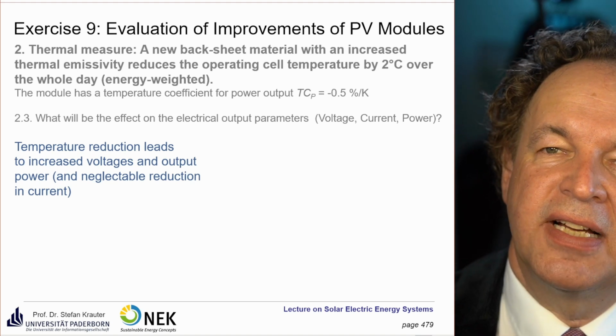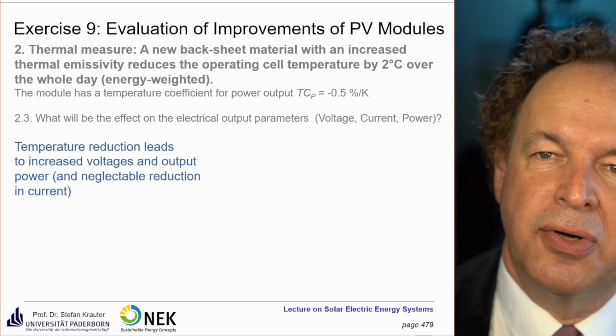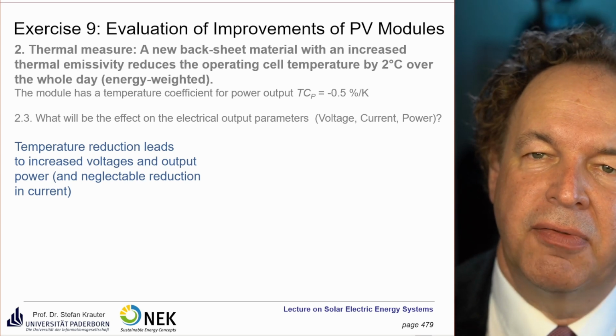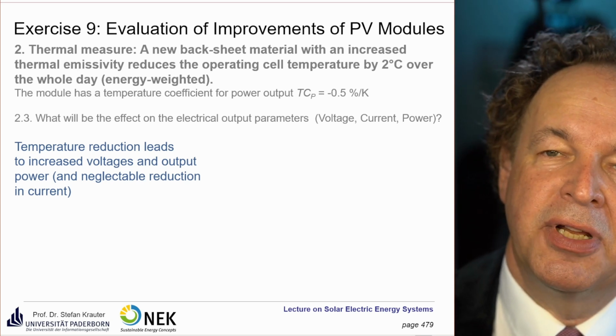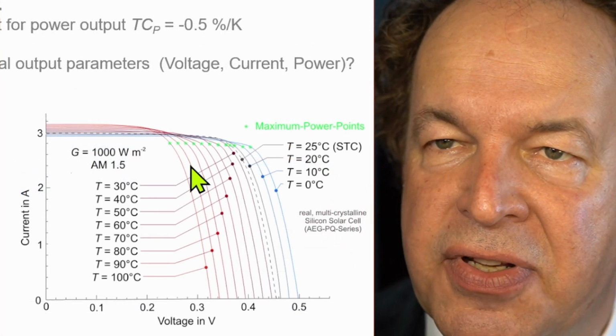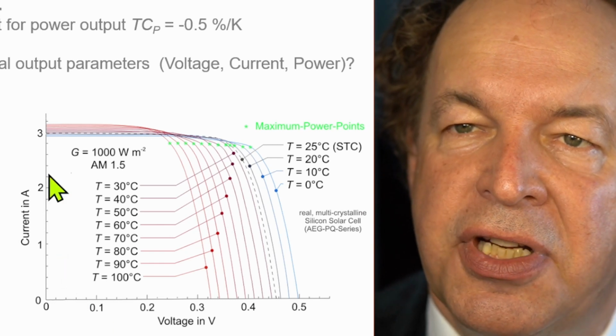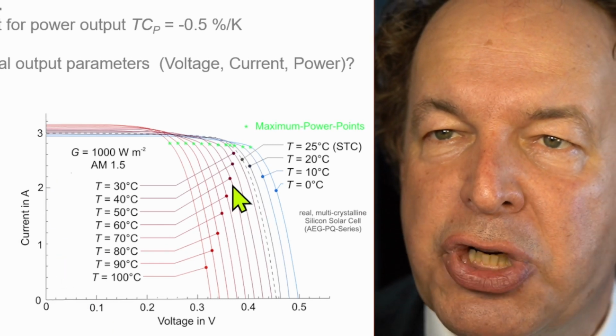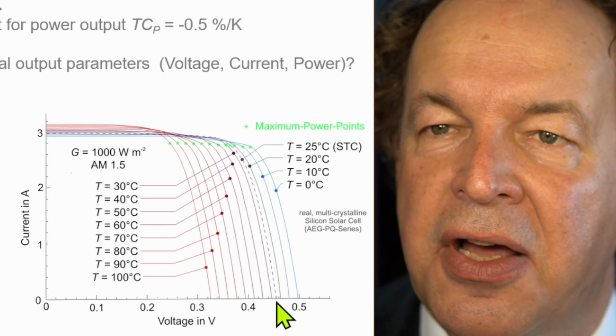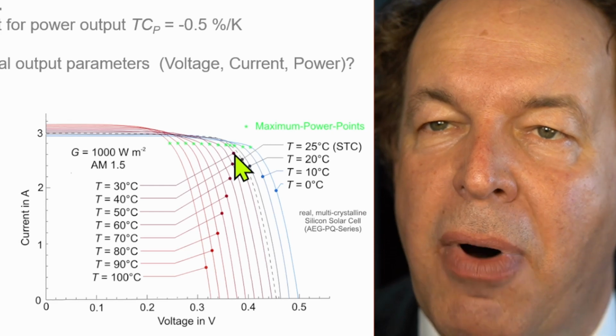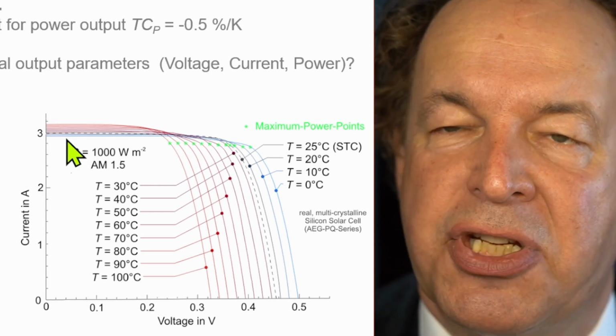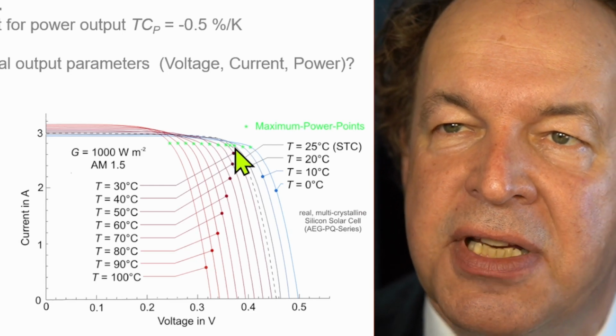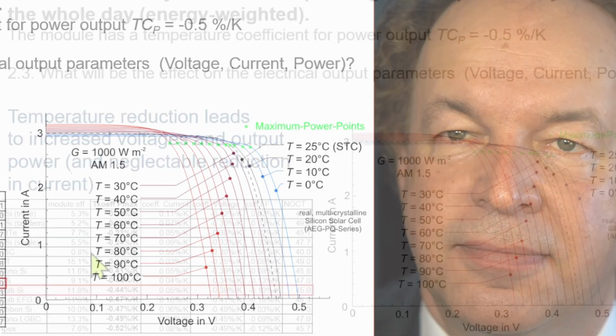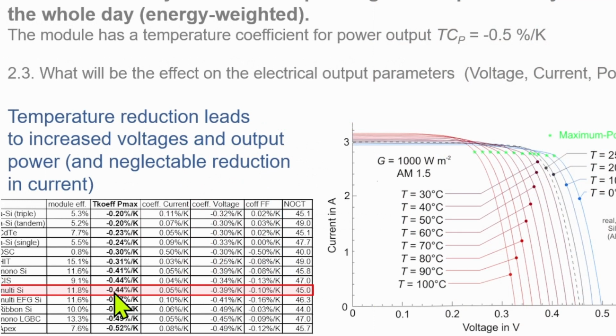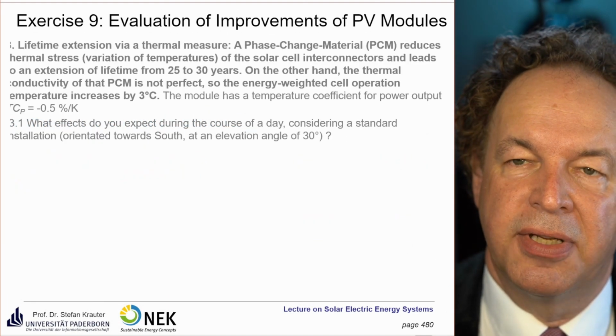What will be the effect of that in terms of electrical parameters? So a temperature reduction leads to increased voltage and also output power with a negligible reduction in current. So you see this curve, remember this from the very first lectures. We have here the voltage and here the current. If you go to lower temperatures towards the blue lines, you increase the open circuit voltage as well as the voltage in maximum power point. You decrease the current, but just a little bit. So the main effect is the increase in power output due to temperature reduction. Here you have the coefficient, which was in the vicinity of minus 0.5 per Kelvin. At temperature increase, power decreases.